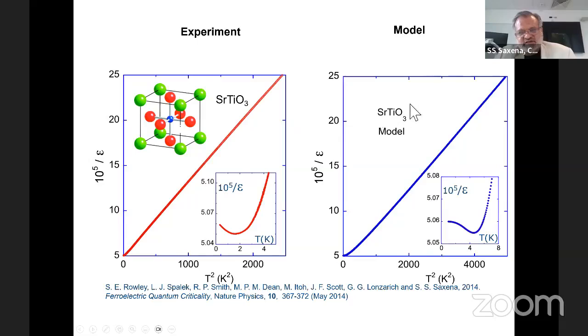You find, in fact, in strontium titanate, if you model it using previous theory, it also qualitatively gives you a similar effect. This was, in fact, originally already discussed by those 73, 79 papers that we're talking about, but they were never able to fully measure it and tune it. And this is where our contribution comes in.